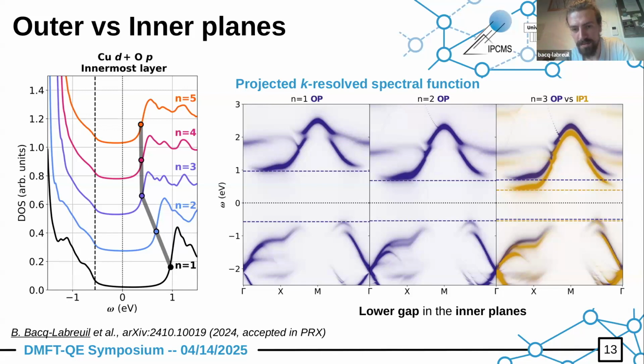So this basically is the sign of spin polaron physics. Okay, so what you are saying is that there are strong but short-range antiferromagnetic correlations, and that those are enough to reconstruct the Fermi surface, producing a pocket around the nodal point. Can you quantify the correlation length? In the calculations you did, do you have an idea of what the antiferromagnetic correlation length is for those